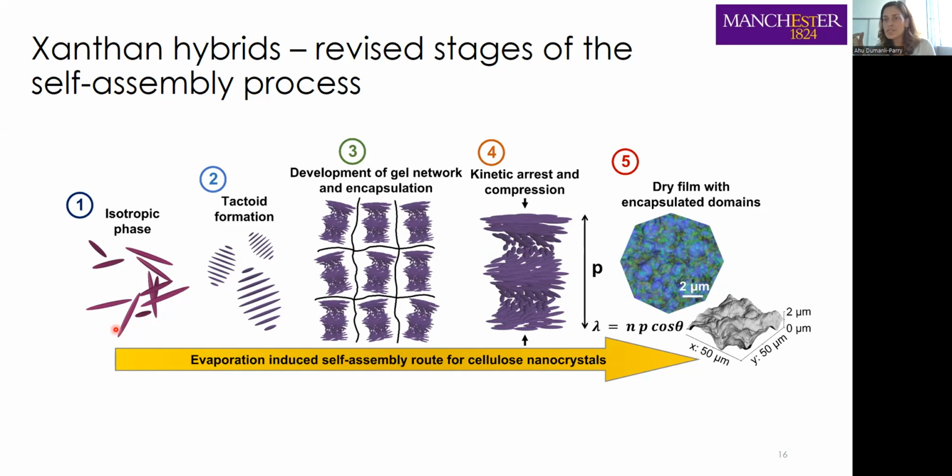And with very small amounts of xanthan, you're able to produce quite viscous gels, actually. A nice thing about this viscous gel is it has very good shear thinning behavior. So this high shear thinning means it flows very easily, even though it has very high viscosity.